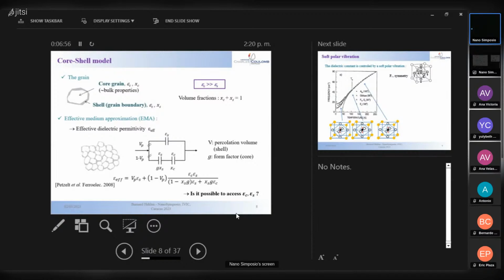sample. And the shell is not of the same material but distorted. It's distorted, and so as it is distorted, it does not have the same permittivity. And so you have a kind of composite with two materials made of exactly the same chemical elements, but one is perfect and the other one is distorted. And so you have the permittivity of the core, which is much higher than the permittivity of the shell.